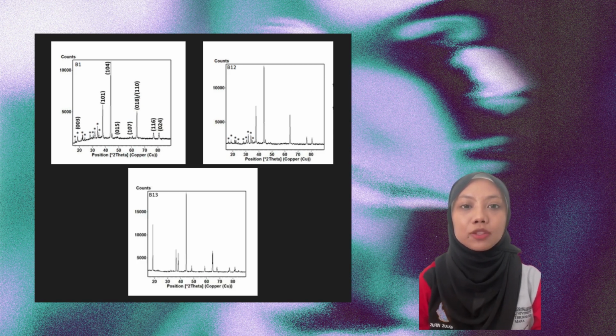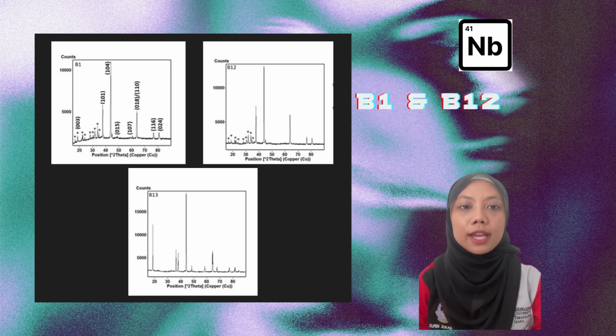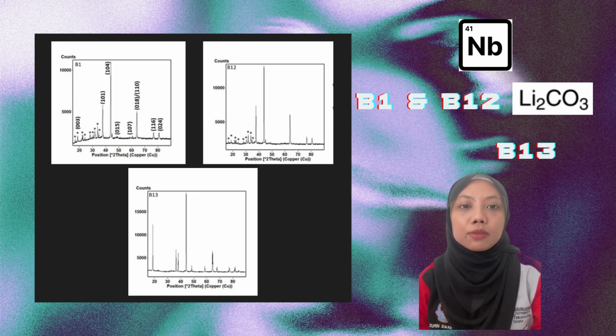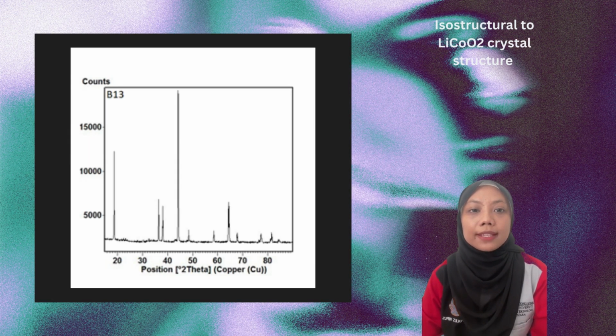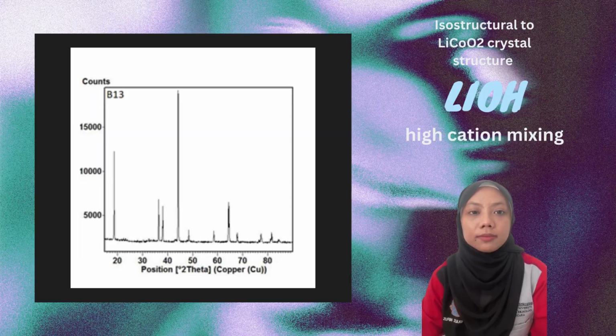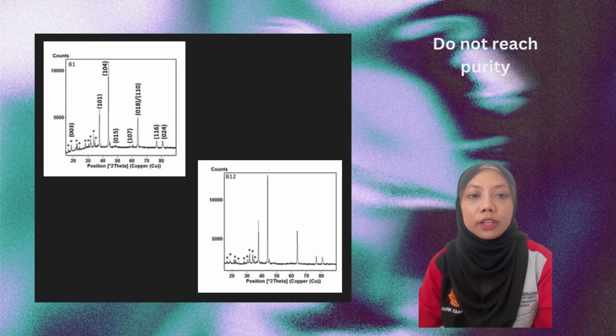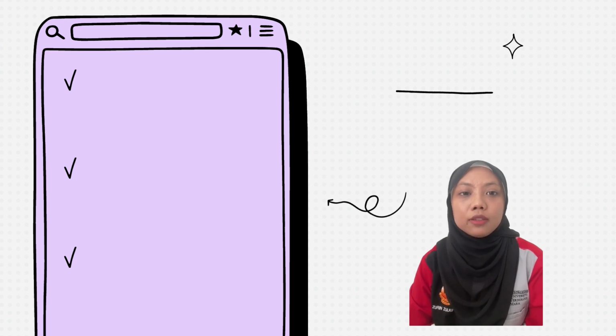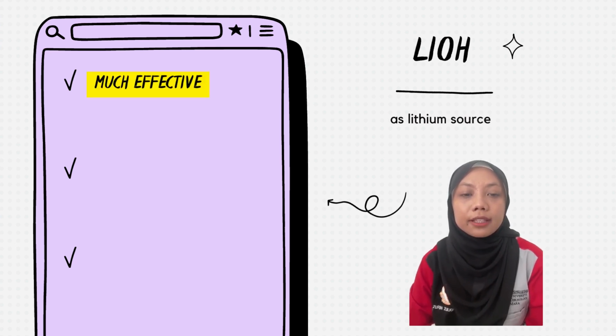The figure shows the XRD result for B1, B12, and B13. These 3 samples use the same dopant, which is niobium, but a different lithium source for each sample. For B1 and B12, both Nb dopant mixed with lithium carbonate, while B13 mixed with lithium hydroxide as their lithium source. XRD patterns reveal that only the B13 sample was isostructural to the LiCoO2 crystal structure of the reference, which is the sample mixed with lithium hydroxide, and this structure has higher cation mixing. However, B1 and B12 do not reach purity as the reference pattern because these samples use lithium carbonate. Thus, it can be concluded that using lithium hydroxide as a lithium source is much more effective to produce pure and single phase of layered structure.